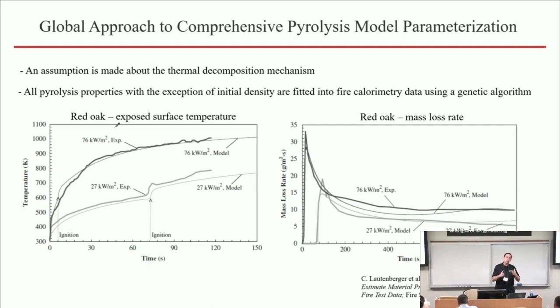In other words, to what degree do the parameters derived this way actually represent the physical phenomena that occur in this system? And I think that to a large degree depends on the quality and availability of the data. The more data you have for this type of optimization, the more conditions you explore during this analysis, the more likely your parameter sets are to carry a lot of physical meaning associated with them. But if the data is limited, then your parameter set is potentially limited in its ability to extrapolate.